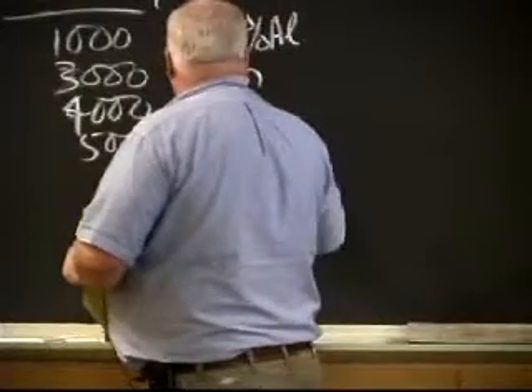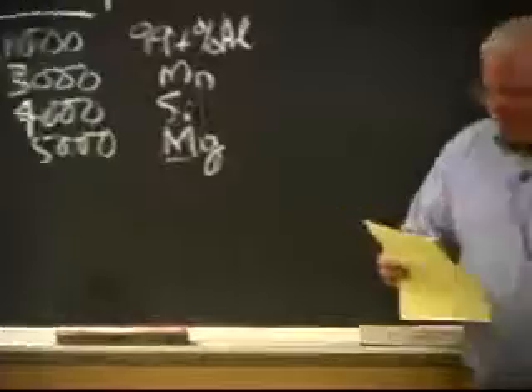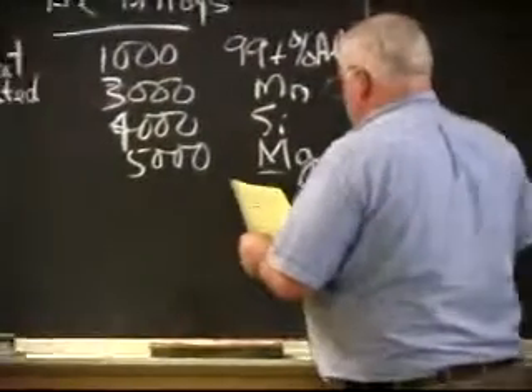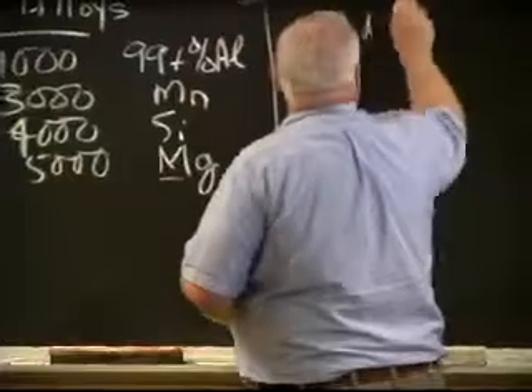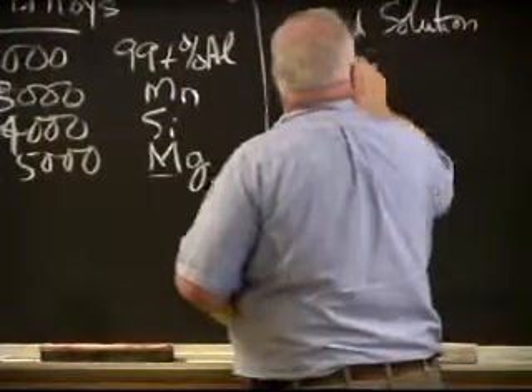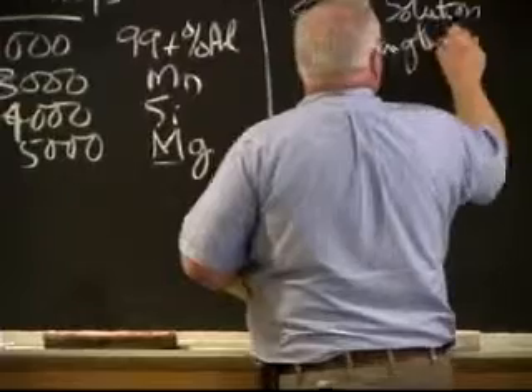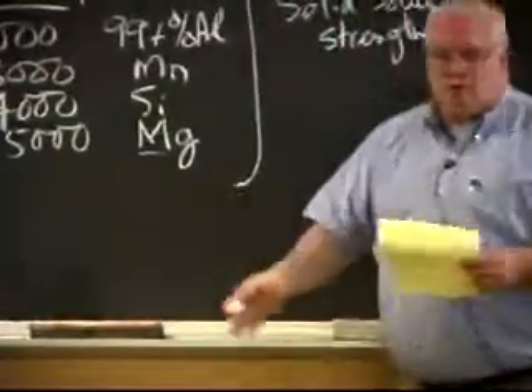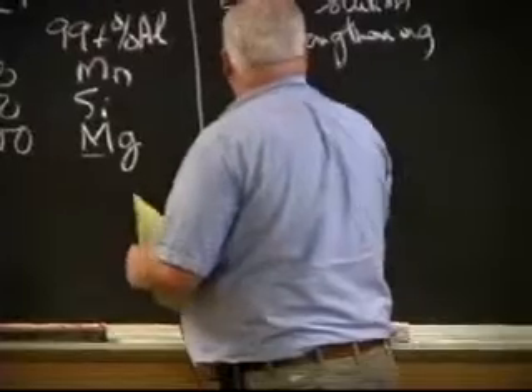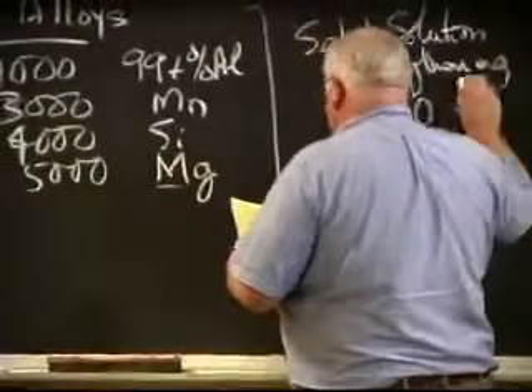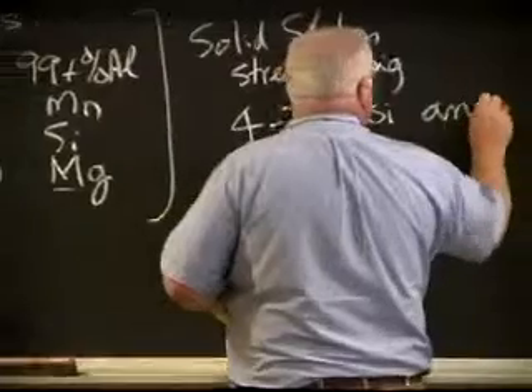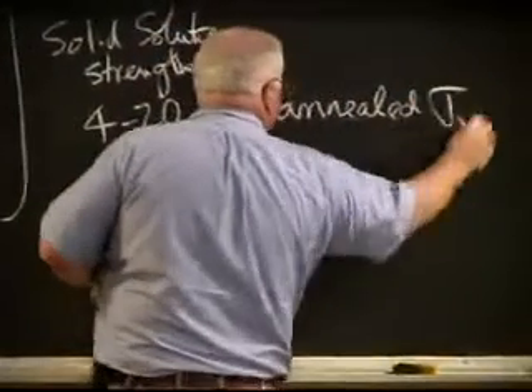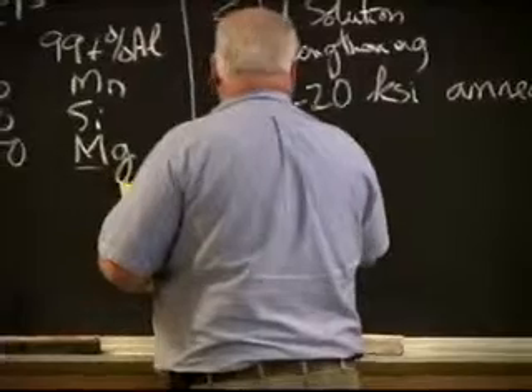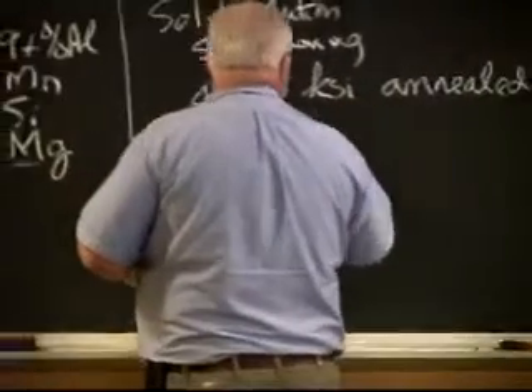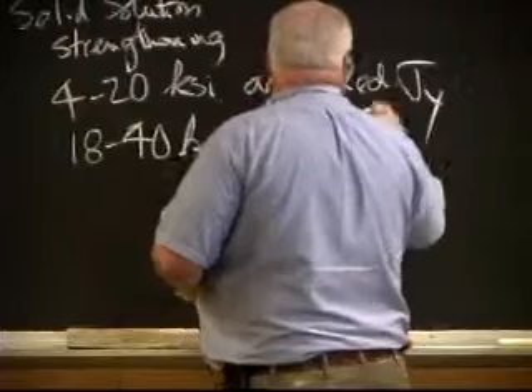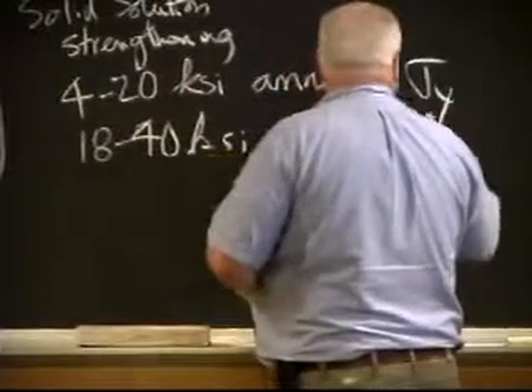5000 series are magnesium alloys, and the aluminum magnesium gives you the solid solution strengthening. Typically, so we're doing solid solution strengthening. Essentially, these elements just go into solution, harden up the crystal lattice against dislocation movement. These will have 4 to 20 KSI yield strength in the annealed condition, and they'll have 18 to 40 KSI work hardened. Work hardened means I've done cold deformation on them.